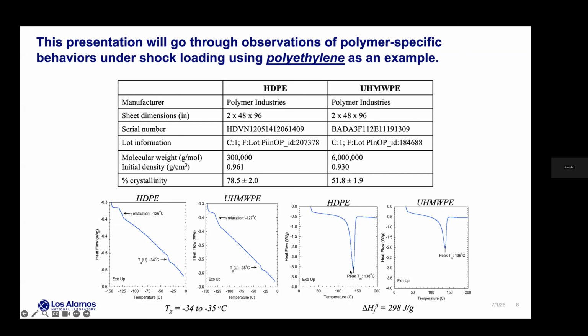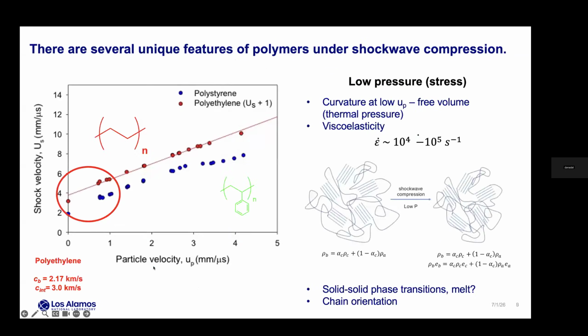The other thing I'll just point out is that if you look down at the lower left corner, you can see the DSC traces, where in this case the exotherms are up, so endotherms down. You can see the much larger melt transition associated with high density polyethylene versus ultra-high molecular weight. And then again, if you look at just the DSC traces, you can also see they both have glass transitions around minus 35 degrees. Okay, so I want to break this down by regime, and I'll use this plot to walk through the rest of my presentation.